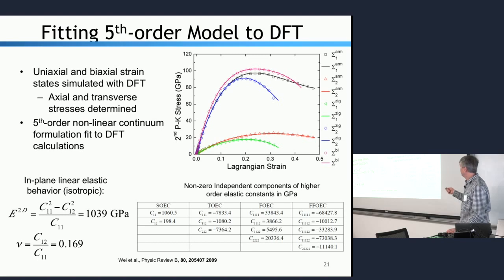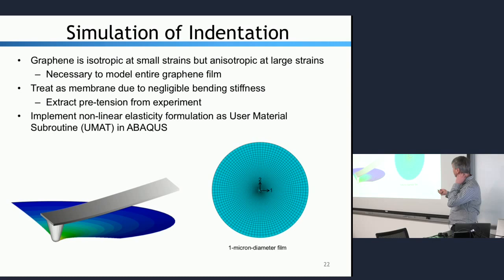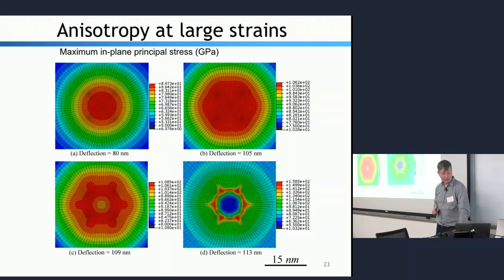So the nice thing here is once you have these elastic constants, you can actually be an engineer again and go back to finite element simulation. So you can plug these elastic constants in to Abaqus or any other finite element code, and you can actually do these simulations now with this much better model for the mechanics of graphene. And so what you can see is a few things. So now if we're plotting here stress, right, as a function of position in the membrane as we indent in the center, you can see at relatively moderate deflection, we get isotropic response. This is what you expect for linear mechanics of graphene. Right? The stiffness is independent of direction.